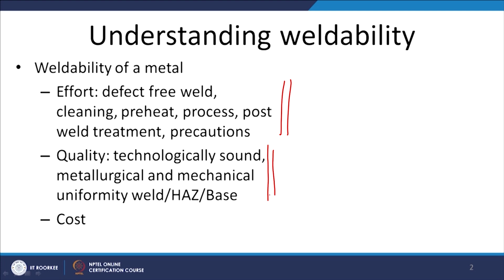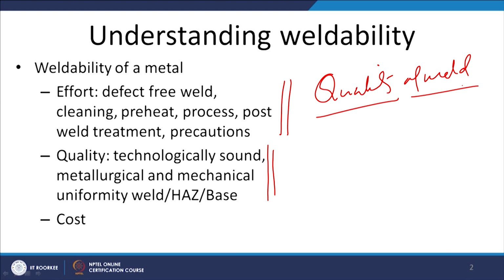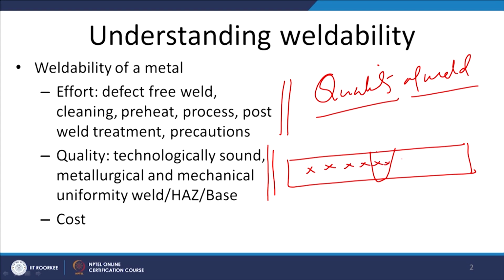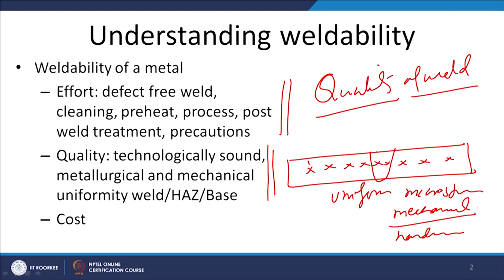We have also to see, for assessing the weldability of a metal, what kind of quality of the weld joint is produced. Quality is a very generic word. So, to assess the quality of the weld, we would like to see what kind of uniformity in mechanical and metallurgical properties exists when a weld joint is developed. For required performance during the service, it is important that across the weld joint, from one side of the base metal to the other side, it has by and large uniform microstructure and mechanical properties, which we normally measure using hardness. So, if the microstructure from the base metal to the heat affected zone to the weld metal and again heat affected zone to the base metal, if everywhere the microstructure and mechanical property is the same, then we will consider that the quality of the joint is good.